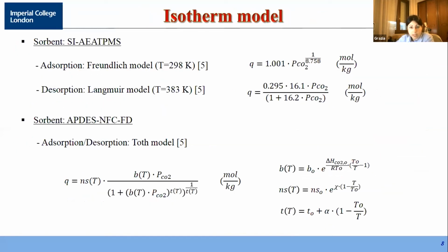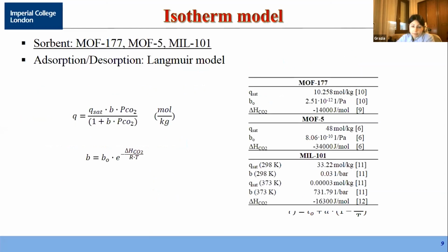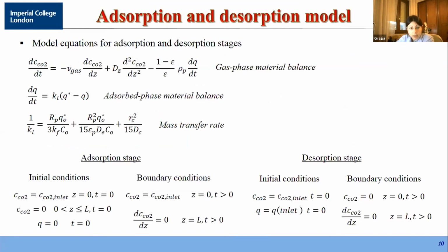For each sorbent, we defined the isotherm model that we considered according to the literature works. In particular, for the silica gel-based sorbent, we considered a Freundlich model for adsorption and a Langmuir model for the desorption, while for the cellulose-based sorbent, we considered a Toth model for adsorption and desorption. For metal organic frameworks, we considered a Langmuir model for adsorption and desorption. Here are the model equations to describe the adsorption and desorption stages.